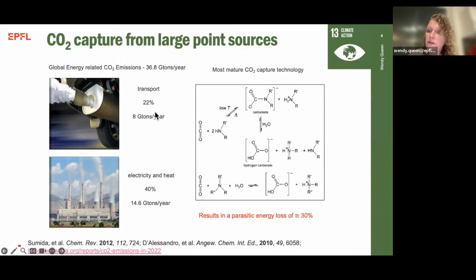So if we look at post-combustion capture, the most mature capture technology is related to liquid amine scrubbers. Now, these are really fantastic materials. They can absorb a lot of CO2 and they can do it selectively. The problem with these materials is that they bond CO2 very strongly. They're also highly diluted with water, which means they have very high heat capacities. And as a result, in order to release that captured CO2, it requires a lot of energy input.